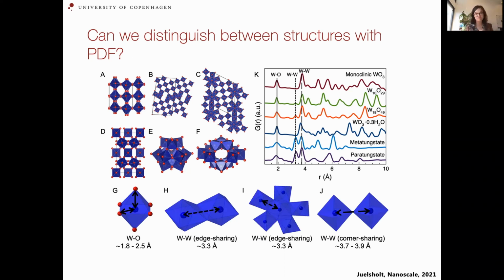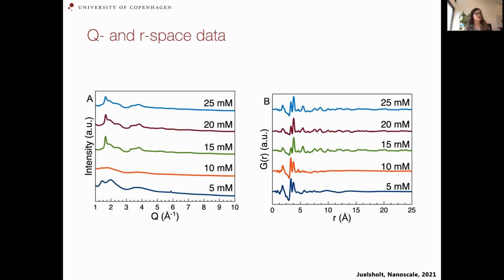So these structures will have different ratios of this peak, because we have different amounts of edge and corner-sharing octahedra. And then, of course, there are also distances that are different further out in the structure, because that's where we start having the arrangement of all of these polyhedra sitting together. In tungsten oxide, these were solid state structures, but you can also make what are called polyoxometalates, which are very well known as large ions like these here. And we can actually also distinguish these from PDF, and we'll get to that in a little bit. Okay, so these are the Q-space data, and then we went to a synchrotron to collect these because we need high quality, high energy synchrotron data to do PDF.